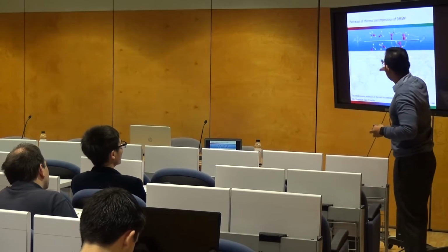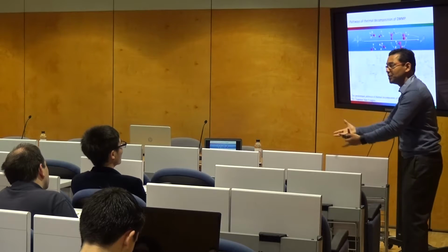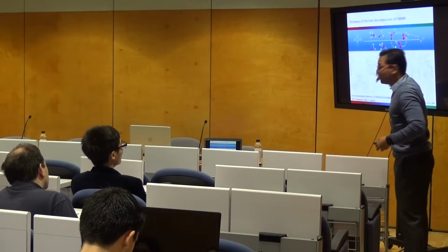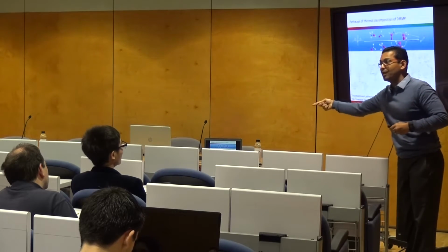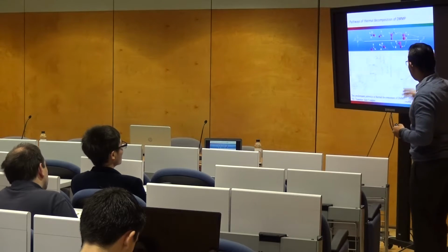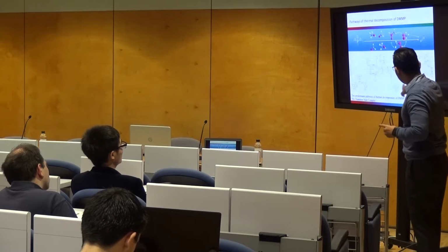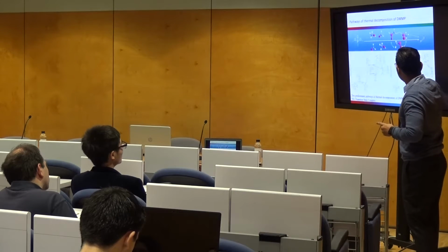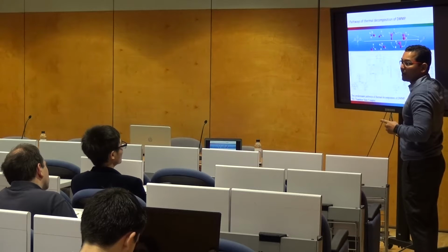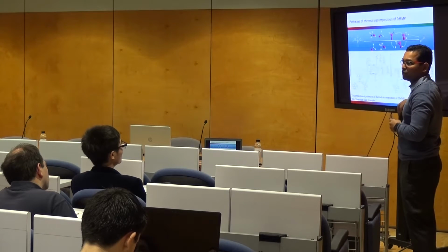So what I'm trying to say here is if we can find nice molecules which are able to produce PO radical much more efficiently, by studying the energy diagram, we are able to design better flame retardants. Okay? So what we are trying to do here, which nobody else has done till now, is to find all the fragments which lead to this PO radical being formed. And that's what we are trying to do actually.